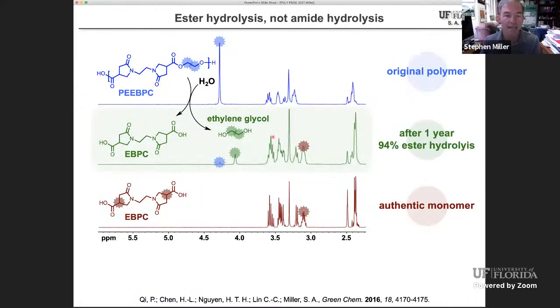We can actually take an NMR after a year to see what's going on here. And in fact, we do see regenerated ethylene glycol. We do see regenerated diacid monomer, looking exactly like the authentic monomer before we started the whole process. And by integration, we see about a 94% ester hydrolysis after the course of a year. So this thing has essentially gone to dimers and maybe a few trimers after the course of a year, just sitting in water, orbital shaker, under neutral conditions.